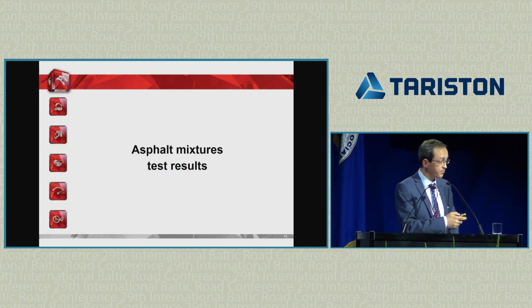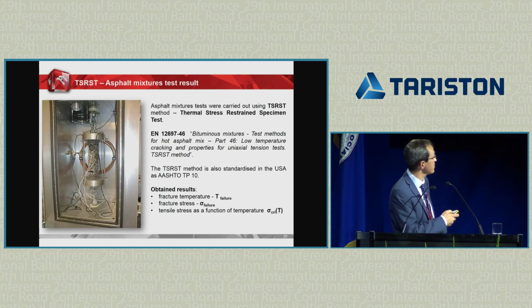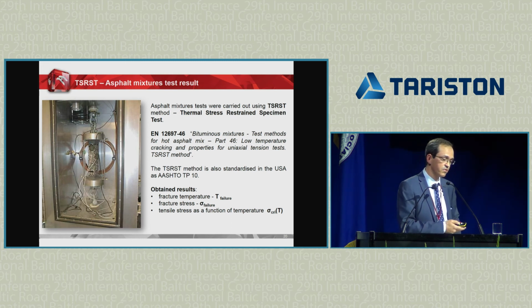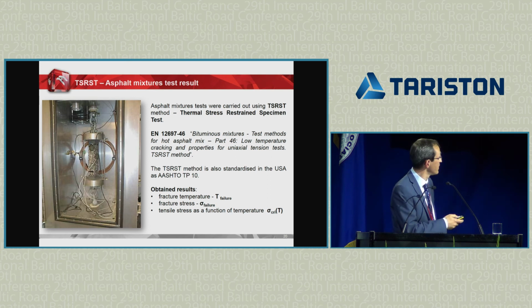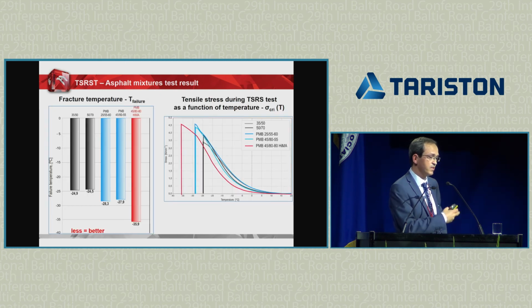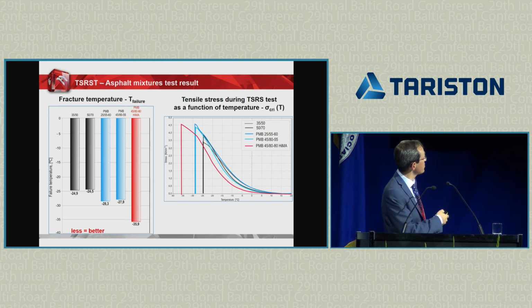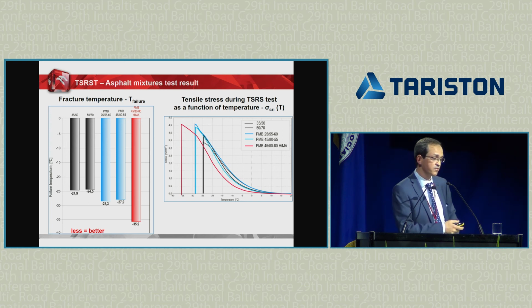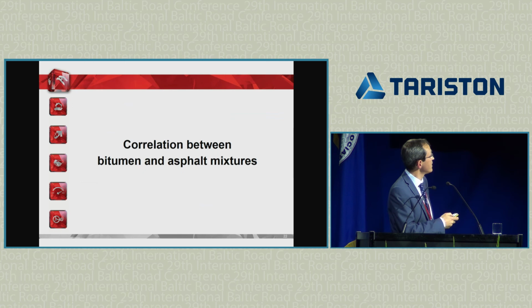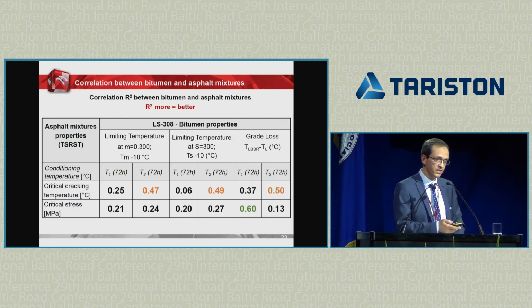Then we tested asphalt mixtures according to the well-known method, TSRST. This is a method not especially for physical hardening, but for thermal shrinkage. And for this purpose, it is a very good method. And the results are for the same laboratory prepared samples. You can see that there are three visible groups: unmodified bitumens, modified and highly modified bitumens, and then the temperature of cracking. There are also three groups with the special superior result of highly modified bitumen. Some correlations? It's very simple to answer. There are no correlations.